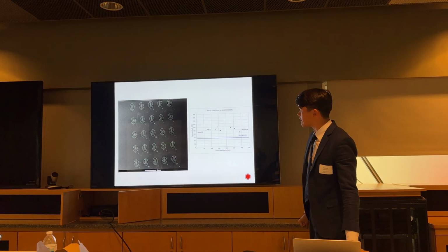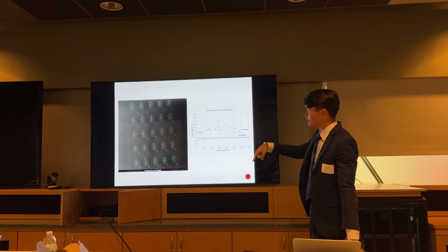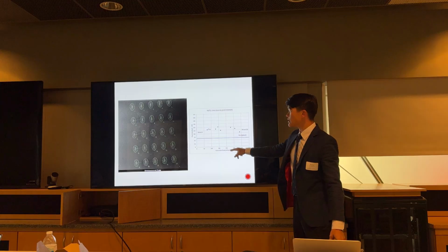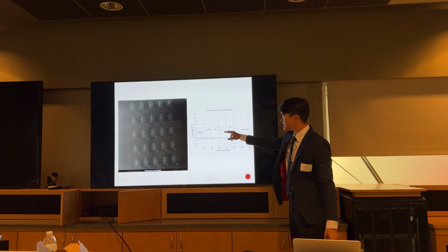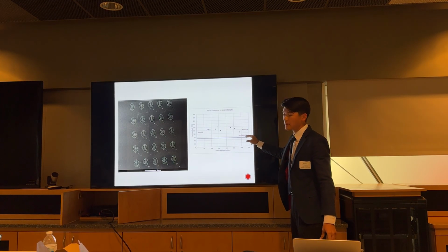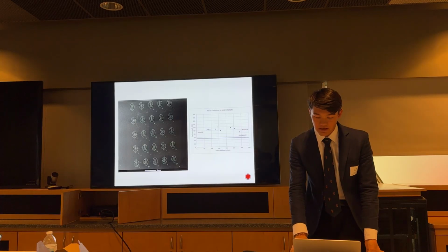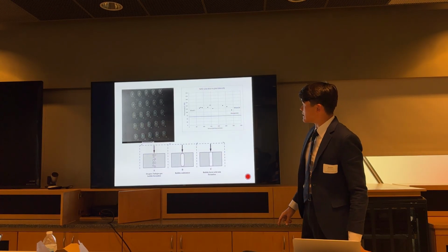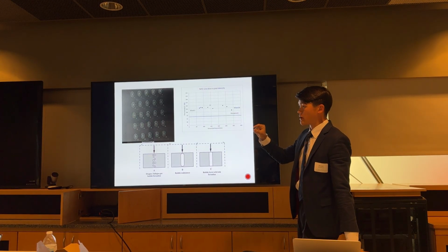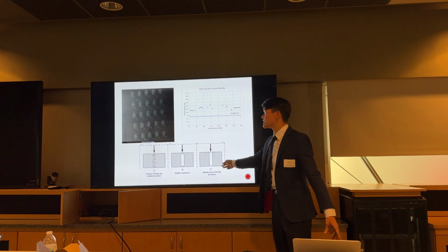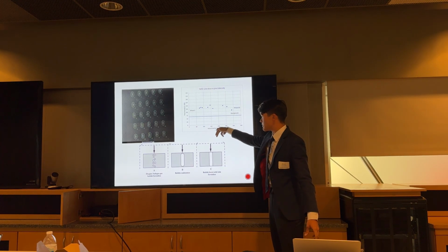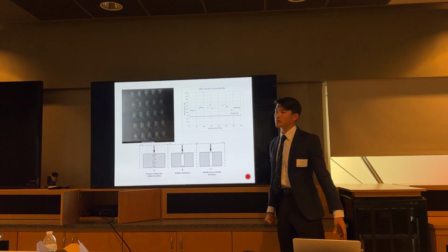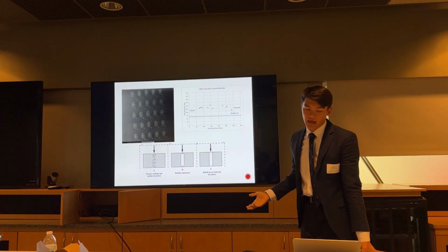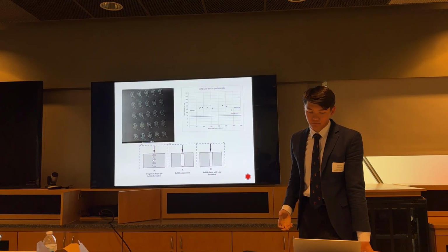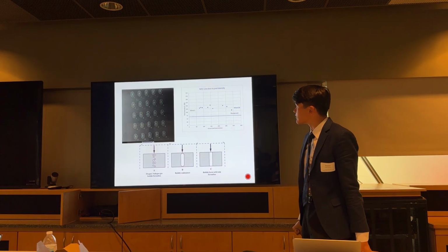Here's another related test, this time with lines, and as the line dose increases, in this case we actually see that the pixel intensity remains the same. This is likely because even at the very lowest dose, the entire layer of ytterbium fluoride was already being completely developed. So any additional dose was simply allowing the electron beam to travel straight through. So we also gathered some data on the properties of ytterbium fluoride.